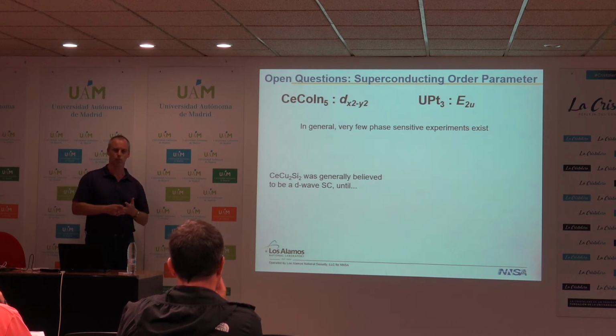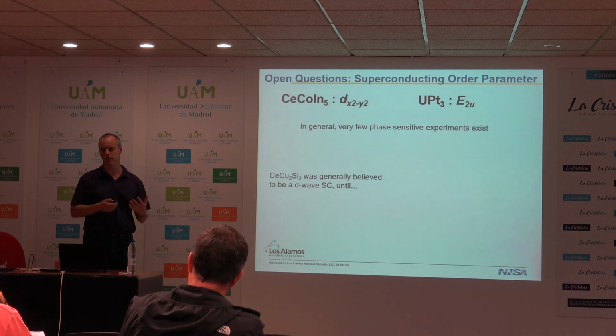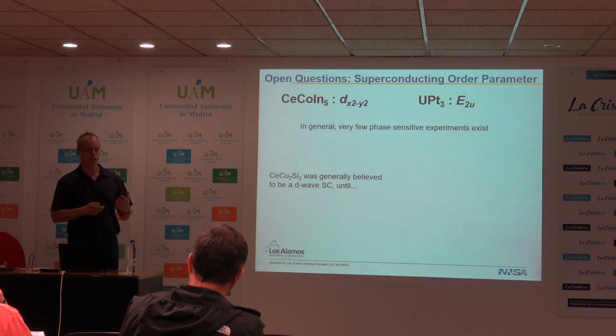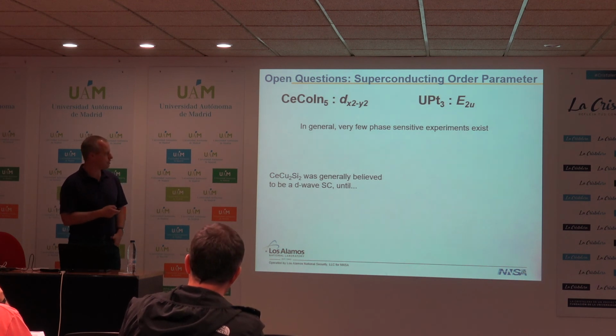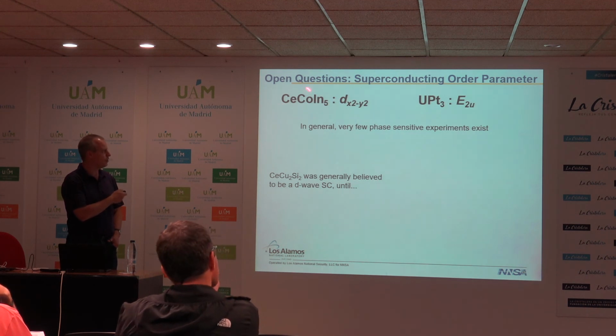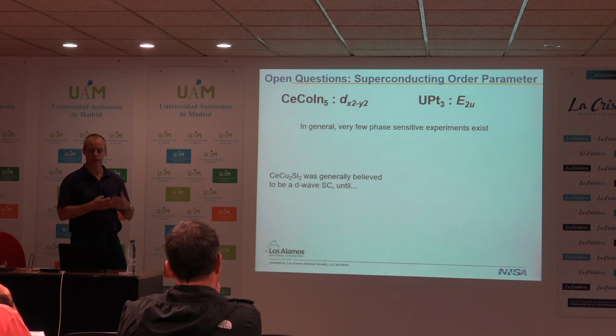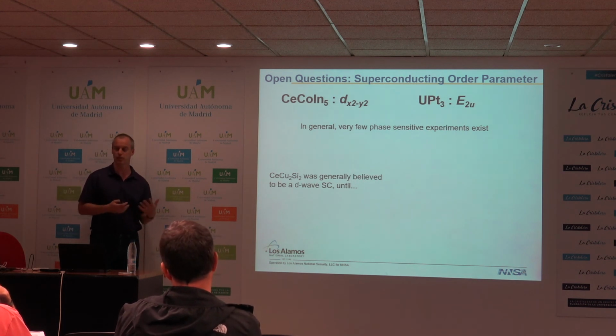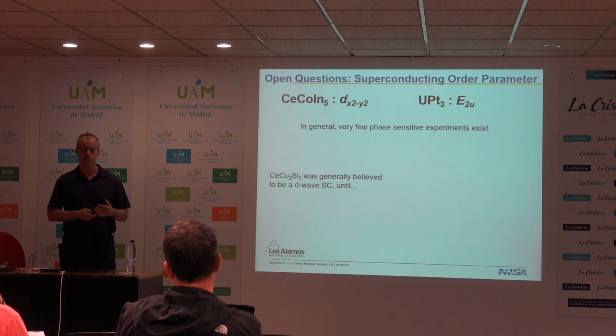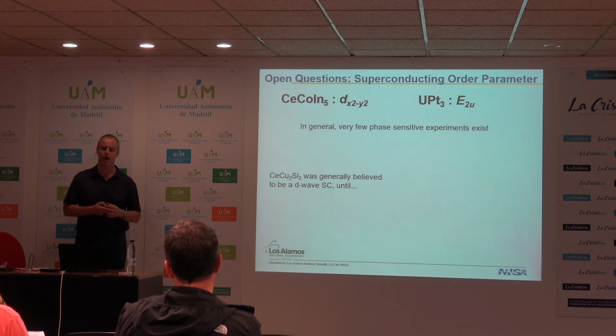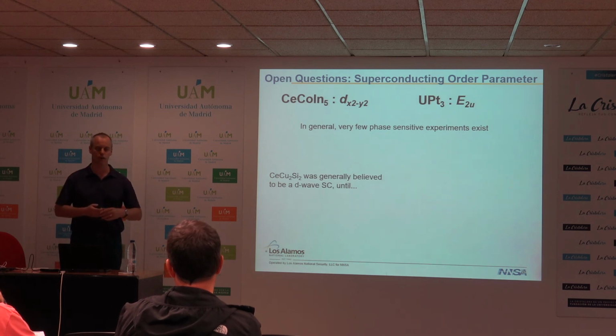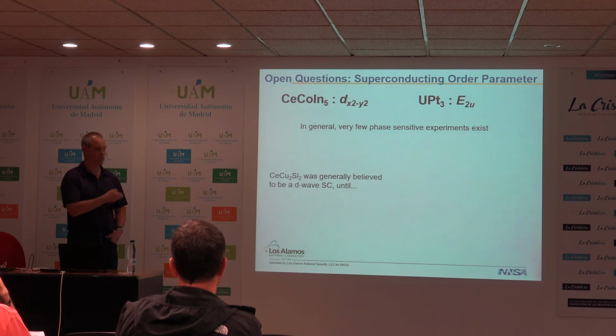And we would love to see the kind of experiments, the Van Harlingen type of experiments, that could establish that the order parameters change sign in these systems. And I think it's a materials issue in general. We're working with cerium, working with uranium, and getting the interfaces of these materials so that you can generate phase-sensitive experiments is difficult. But perhaps in things like STM, where you can look for Andreev reflection and for signatures of the change in sign of the order parameter, is a way to explore these materials more generally.